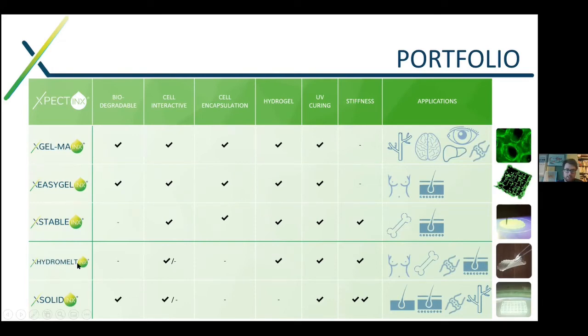So we have our XHydromelt, which is a hydrogel printed from the melt, which can be made cell interactive if desired or not, because for some applications you don't want cell interactivity. It's a hydrogel which is UV cross-linkable and also very robust. And we already managed to use it for different cell types, including adipose tissue, bone tissue, cartilage, and skin.